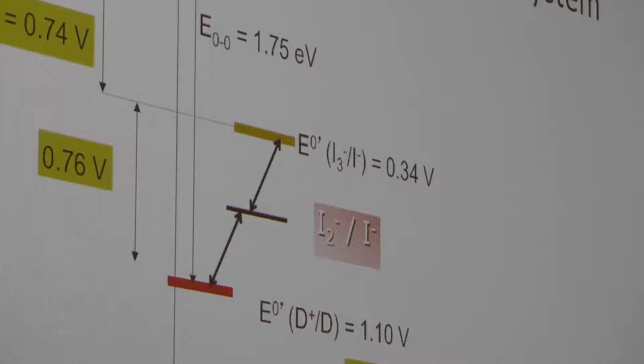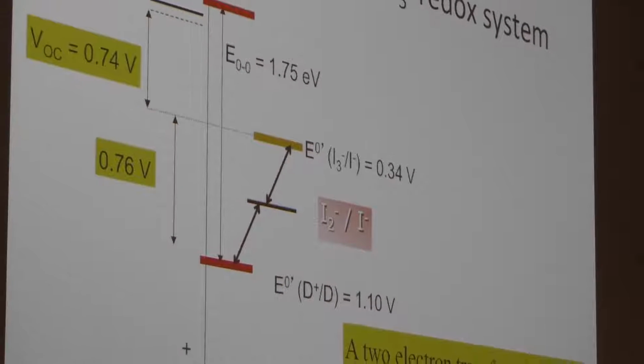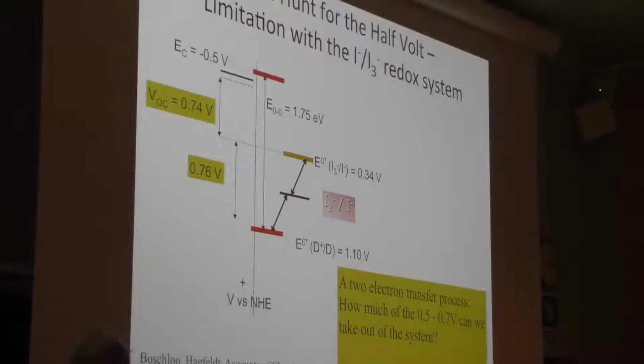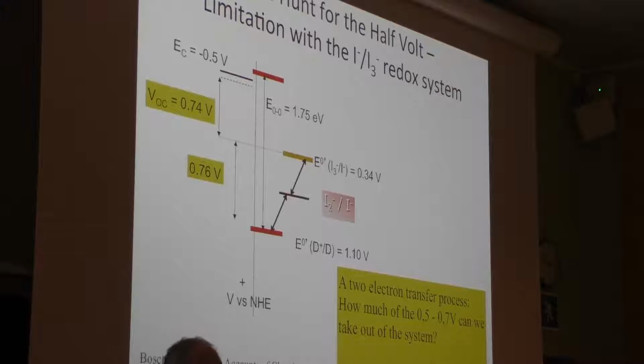We lose potential there, and the benefit on the other hand with iodide, triiodide is that this reaction of electrons here with the electrolyte is very slow. So as soon as you change your redox system to something else, you really open up this process to be much faster. So if you take ferrocyanide, a classical redox system, the problem is really that the electron reacts quickly with the electrolyte. So to solve that problem, you need to passivate the surface somehow.